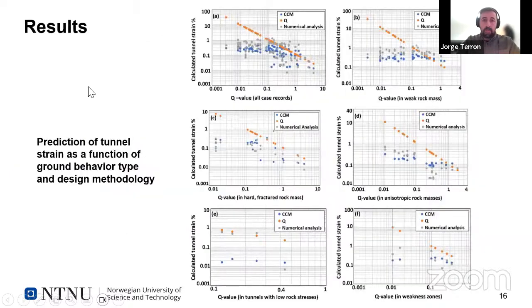So looking into the numerical results, I wanted to first plot the performance of those 3 main design methodologies: numerical, analytical, and empirical. In the first figure, A, you can see all of the results from the 118 cases plotted in the same graph. As you can see, there is an approximately good agreement in the results of tunnel strain between Q value 0.1 and approximately 1 or a bit above 1.